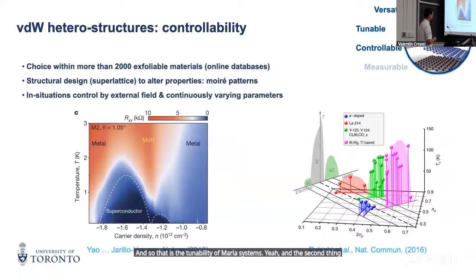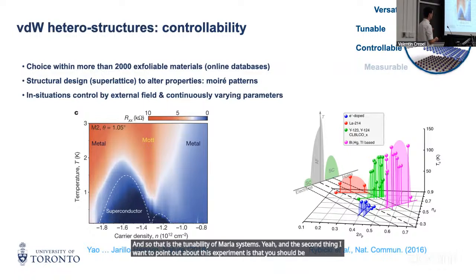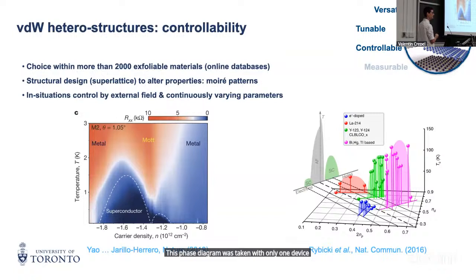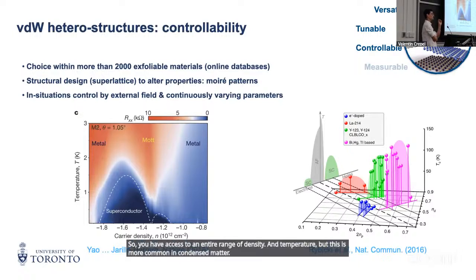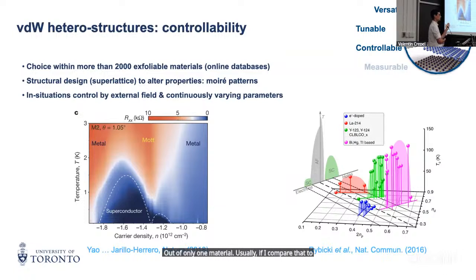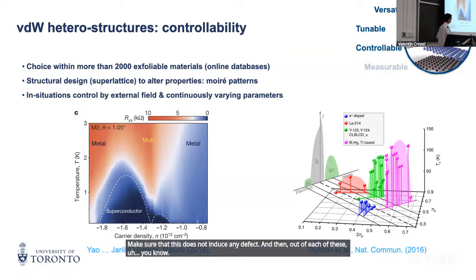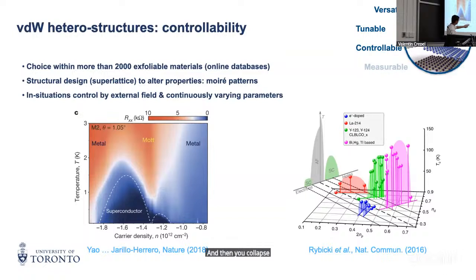Yeah, and the second thing I want to point out about this experiment is that you should be amazed that this phase diagram was taken with only one device, called M2 here. So you have access to an entire range of density and temperature out of only one material. Usually, if I compare that to high temperature superconductors, getting the phase diagram is much harder because you need to grow each sample, like a bulk 3D sample, independently. Carefully dose the number of dopants you put in your system. Make sure that this does not induce any defect. And then out of each of these materials carefully designed, you get one data point. And then you collapse all of these data points for different material classes and hope to get something that makes sense as a phase diagram. And here you really get everything within one sample. And so what took you 20 samples there takes you 1.